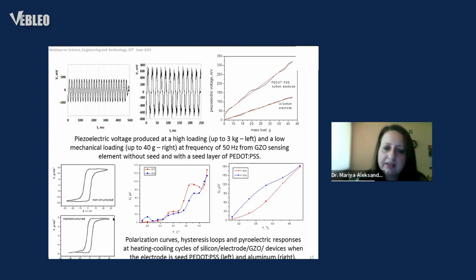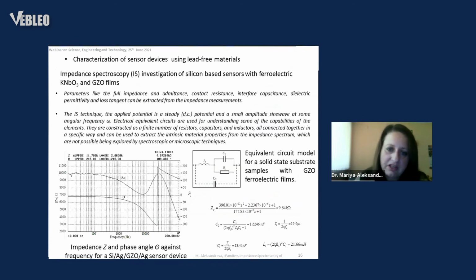And here is the pyroelectric voltage in both cases, nanostructured and non-structured, non-patterned coatings. As you can see, the hysteresis loop, which is the average difference between the cycle of cooling and heating, at the non-structured materials is on average 35 millivolts, which is equal to almost 30%. This is the error in the sensor, and here the average is only 20 millivolts, which is less than 5% of errors. I'm almost at the end of my talk.